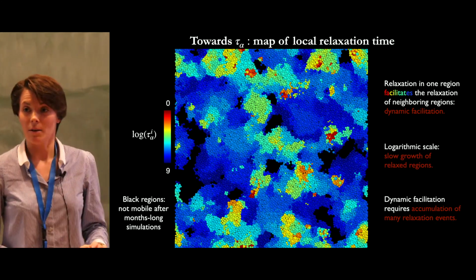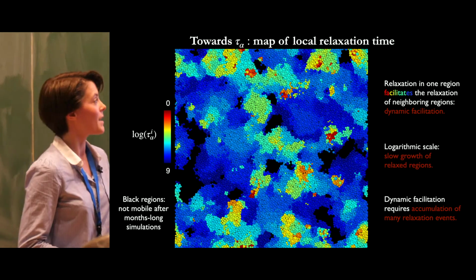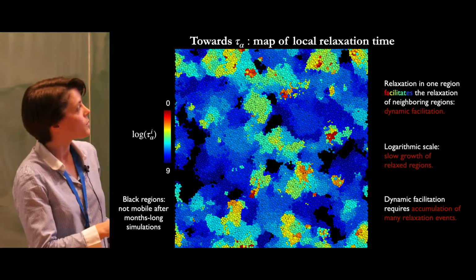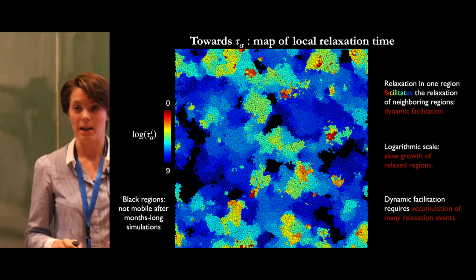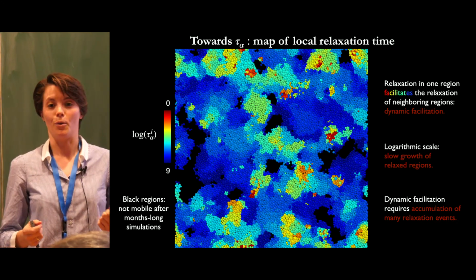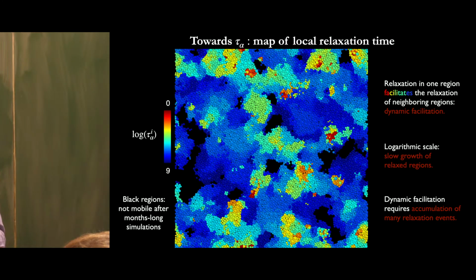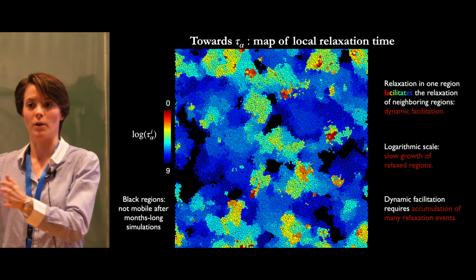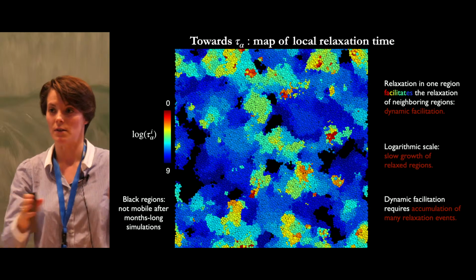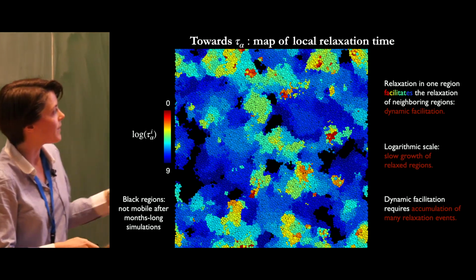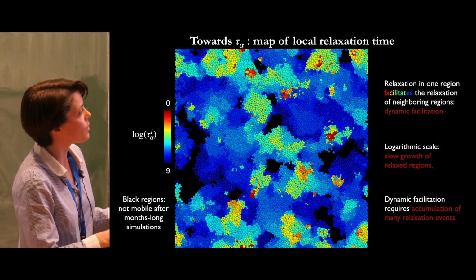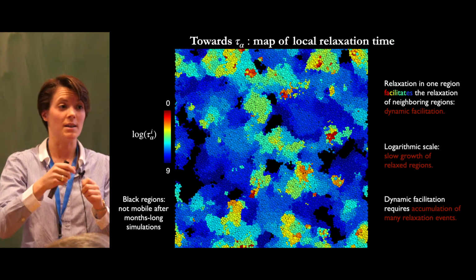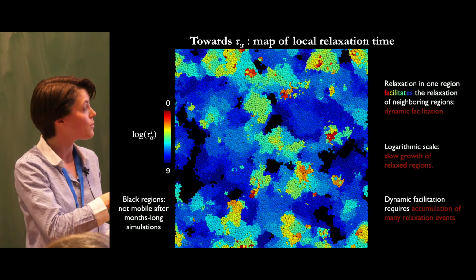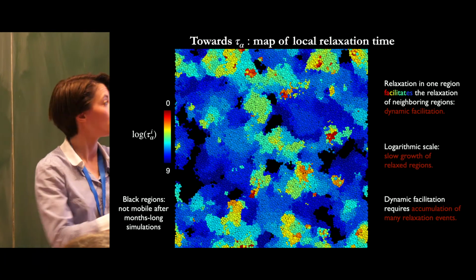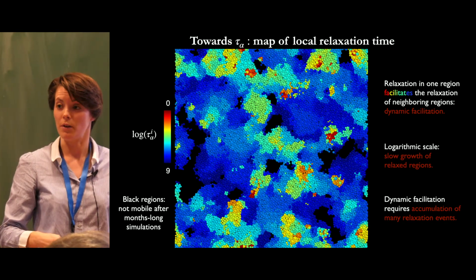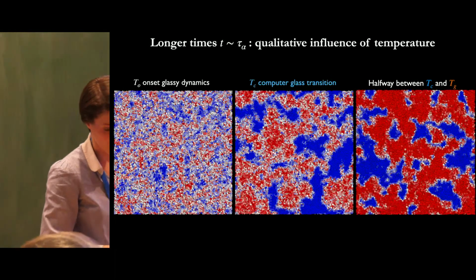Here, something that is actually striking. This is equilibrium dynamics. I insisted on this aspect because it is really important. And I'm showing you the dynamics that's going on in logarithmic scale in time. You should be a bit surprised by this, because this is equilibrium. So in each time frame, you should have the same amount of relaxation events. This is time translational invariant. What that means, the fact that you see this log scale spread, is that you have relaxation events that are taking place in these locations over and over in time in order to eventually relax the neighboring region. And this is something that I will quantify just afterwards.